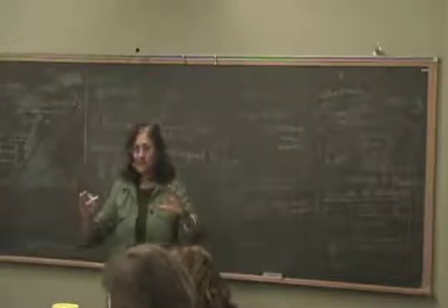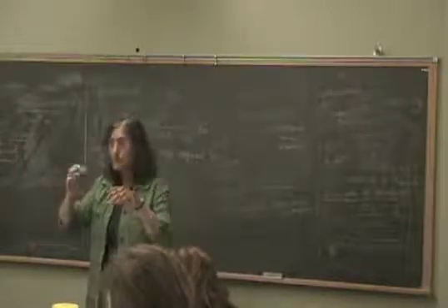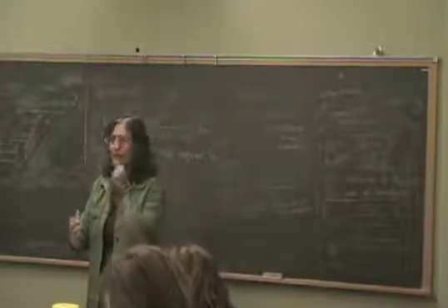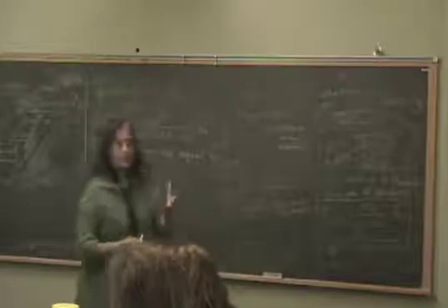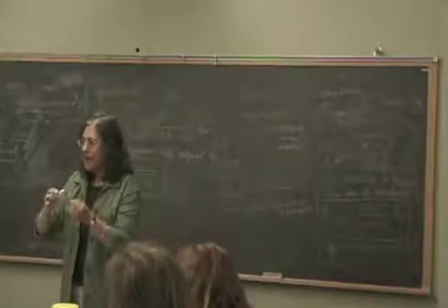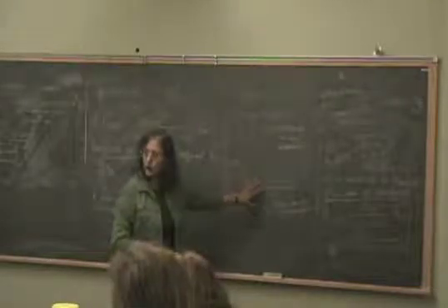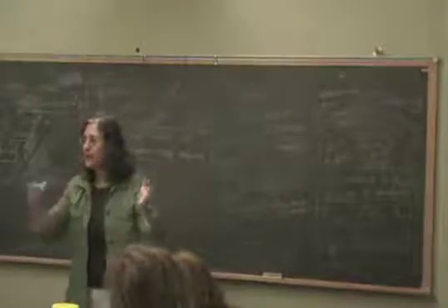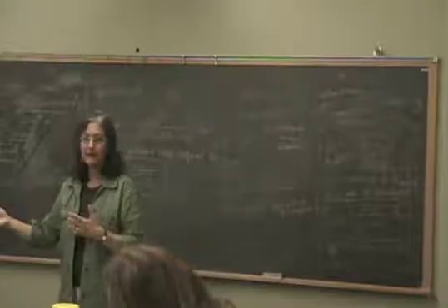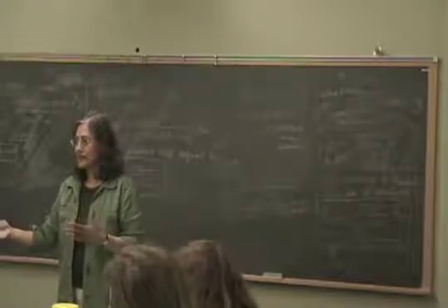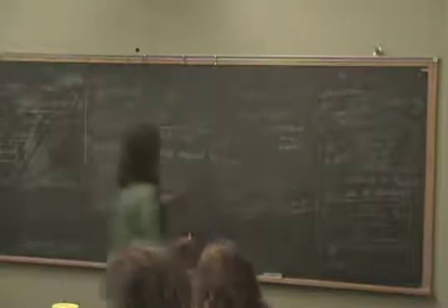Let's think about the material. We have a dielectric, which is also made up of electrons. Most of them are bound very strongly. So until I hit a frequency which is basically the binding energy of that oscillator, I'm practically in the 0 frequency limit of the dielectric. On the other hand, the metal has these free electrons. The moment I apply any electric field, it will start sloshing back and forth and responding. That's why the metal response is much faster. Now we have to be careful. If you start really exciting some of these core levels, which was giving me these big peaks in the dielectric function, then I have to worry about it.